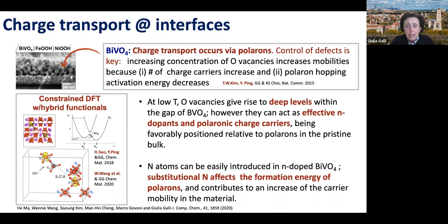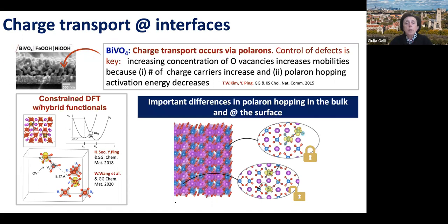And let me skip these details. One important thing that we understood is that there are very important differences in polaron hopping in the bulk and at the surface. You need to know what happens in the bulk, because this is what happens when the light is first absorbed, right? It's absorbed in the bulk. But then you cannot just use what you have learned for the bulk to understand what happens when the charges are given from the solid to water, because the polarons and how they hop at the interface is really different. And so this is what we did in these two works with Hosang and Wenny Wang, and we compared and understood the difference between surfaces. And actually, once the polarons get to the surface, unfortunately, they are less favorable for charge transport than in the bulk, but the process can still, to some extent, occur.